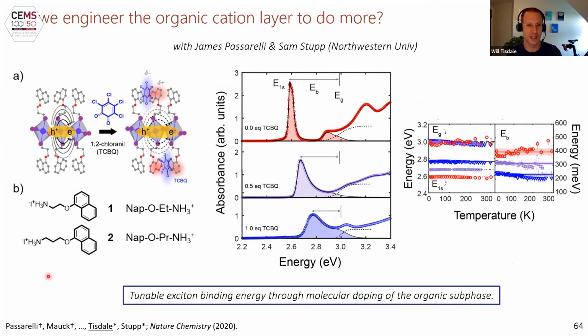This is a collaboration with Sam Stupp's group at Northwestern, where through molecular doping of 1,2-tetrachlorobenzoquinone into a ligand layer that includes a naphthol moiety, the TCBQ and the naphthol form a ground state donor acceptor complex that has a very large dipole moment within the organic subphase. And by controlling the amount of doping, we could tune the exciton binding energy in these materials.